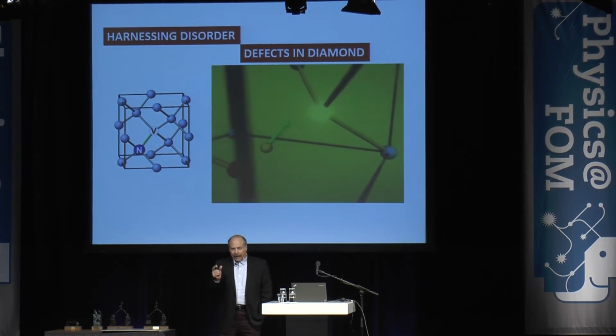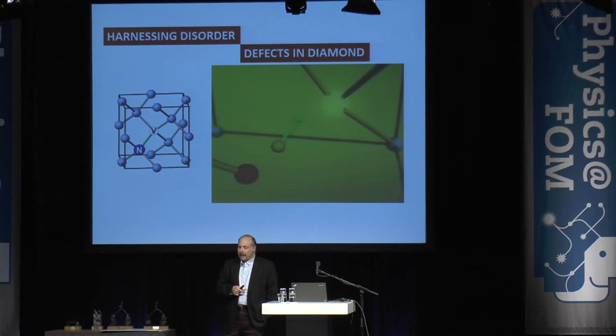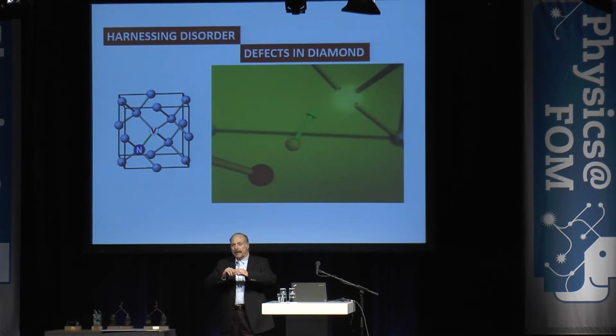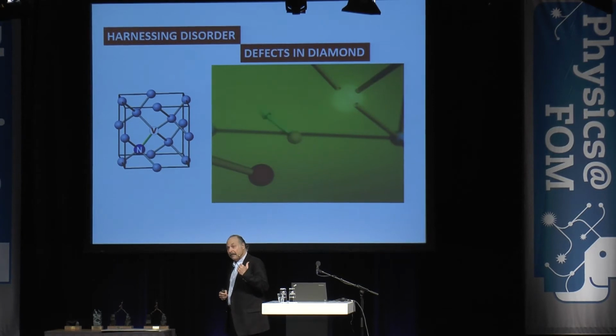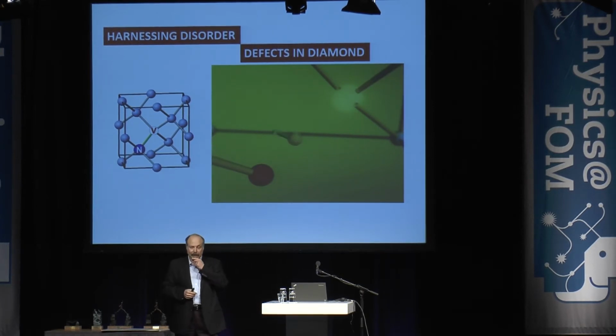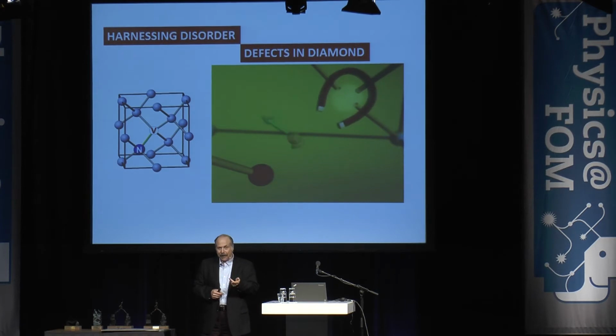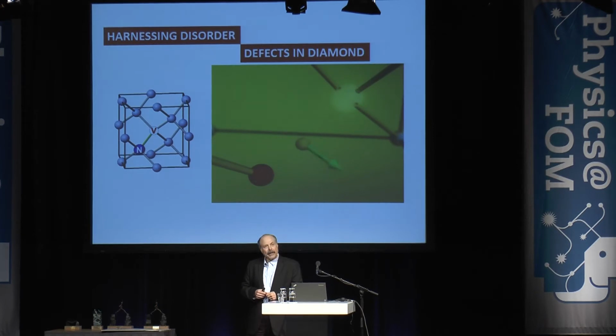And the so-called nitrogen vacancy center that Ronald alluded to earlier: when you pull out the missing atom, you tend to distort the lattice and create a type of molecular state that holds essentially a single electron. And this electron has a spin that can precess at a certain frequency, and you can manipulate it either by illuminating it with light or by applying magnetic fields. Pretty much just like that. You take a magnet and you move it in and out. And you have a very nice quantum object on the desktop that you can play with, something that would have been very difficult to imagine just a decade ago.